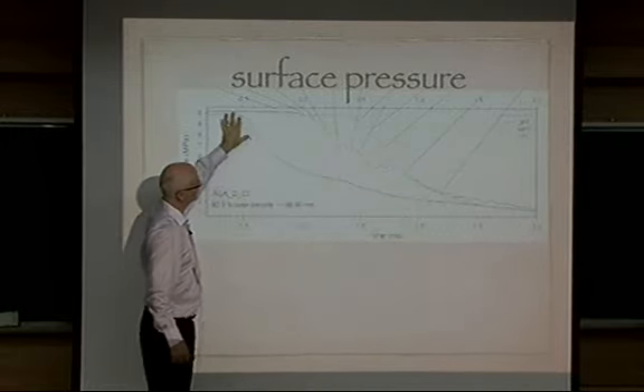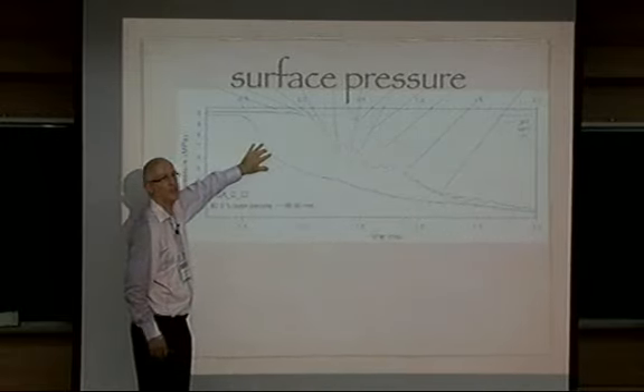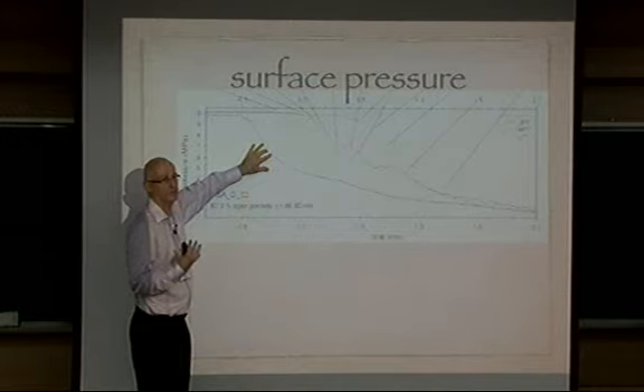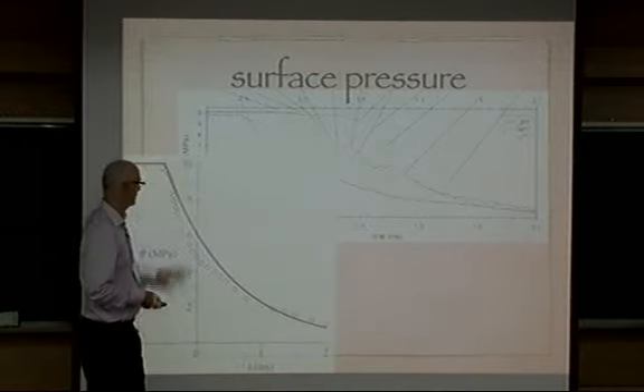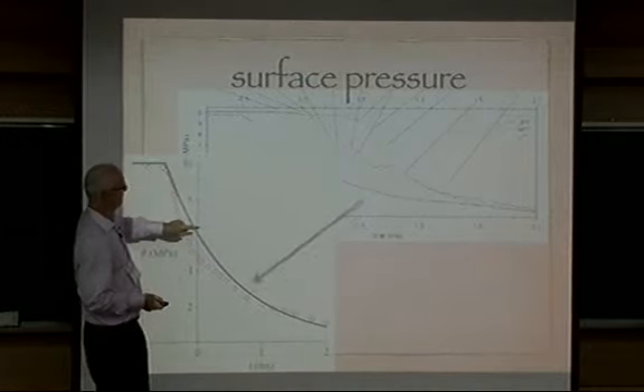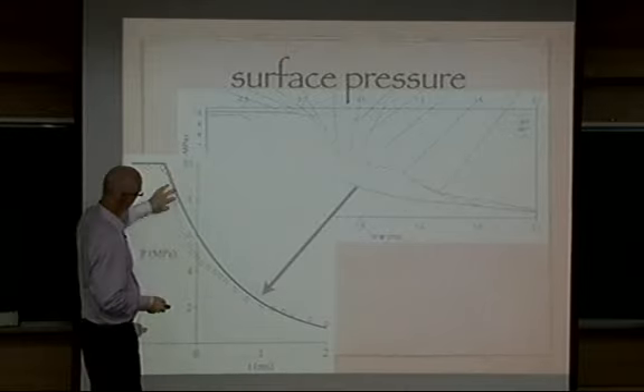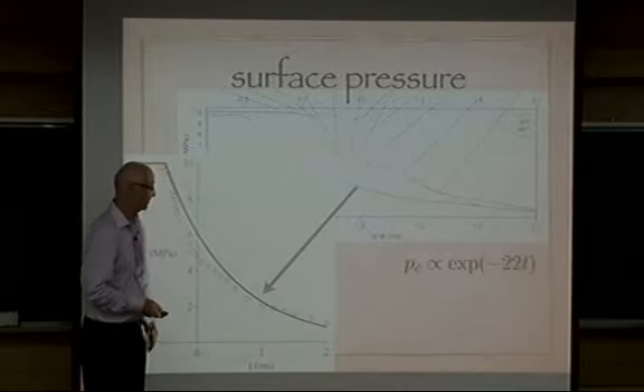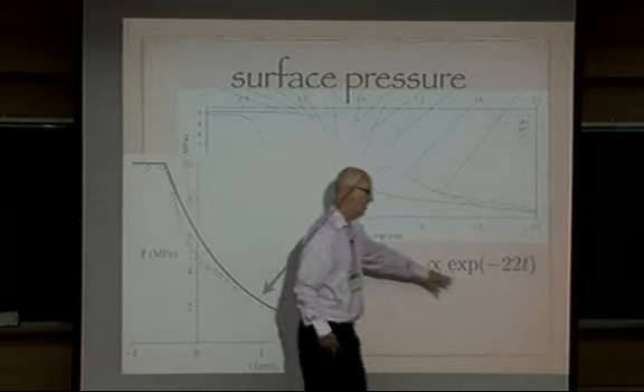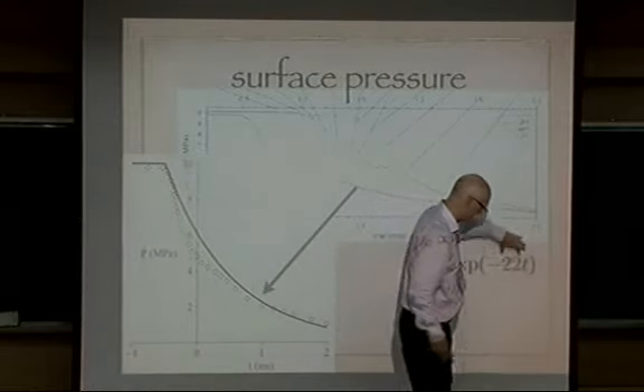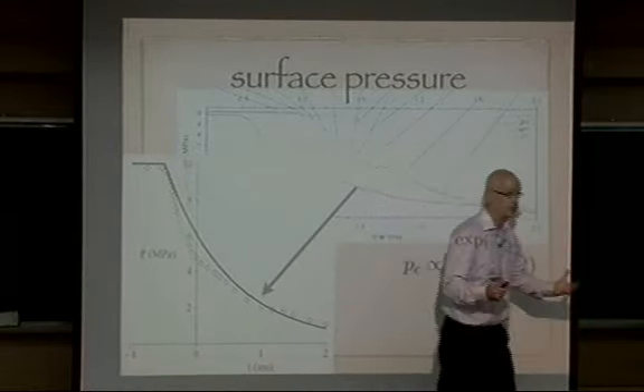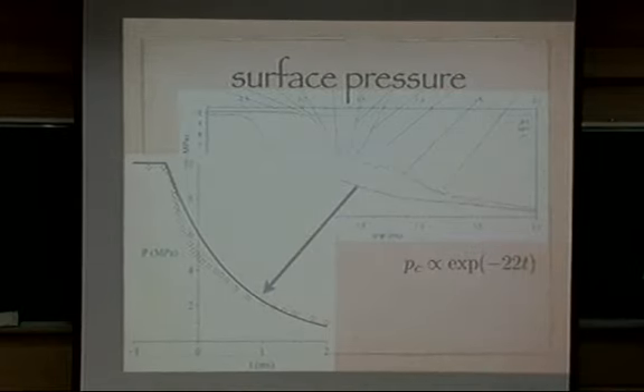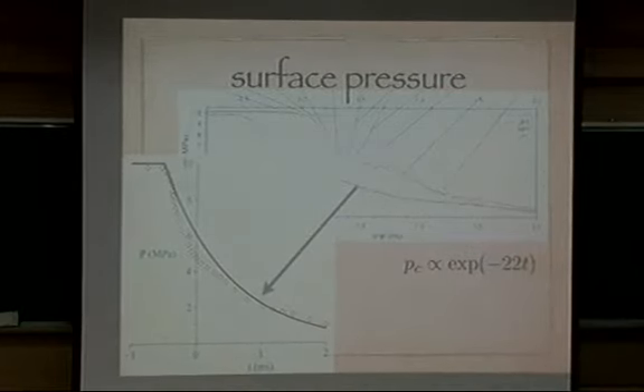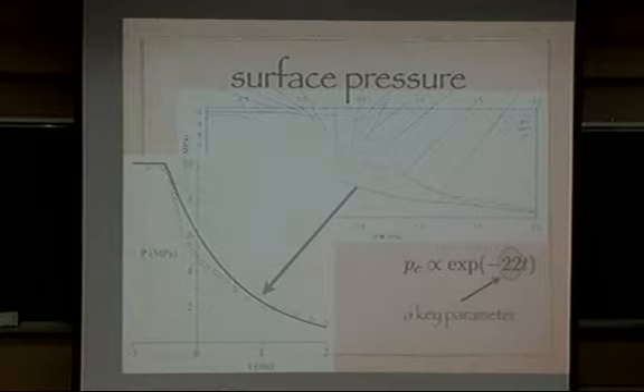So we've got that, and I want to use this to impose that as the surface boundary condition on my pressure diffusion equation. So that turns out, here's the data. So it's this curve here, and I've just digitised it, put an exponential through it. In the non-dimensional time, it's e to the minus 22t. So this 22 is a parameter, and it's the most important parameter. So then solve it numerically.